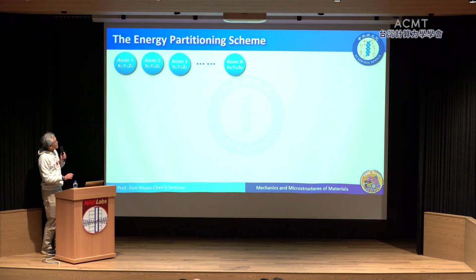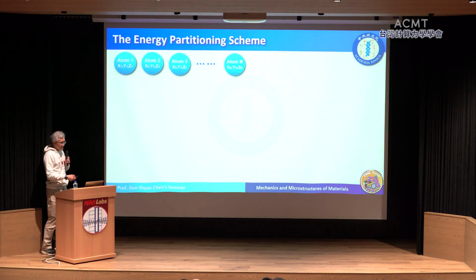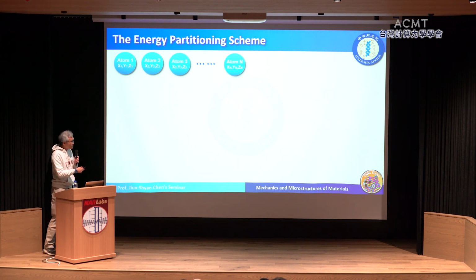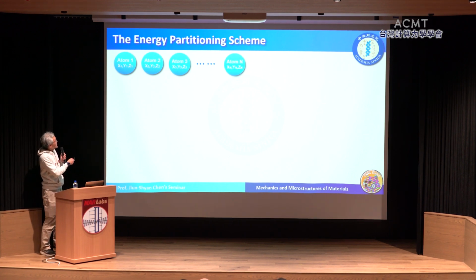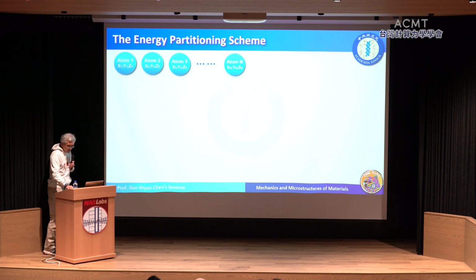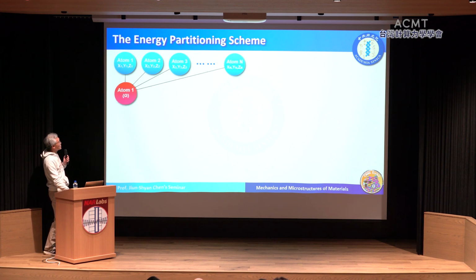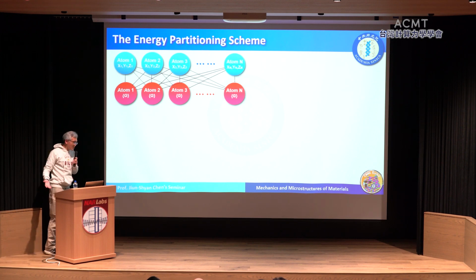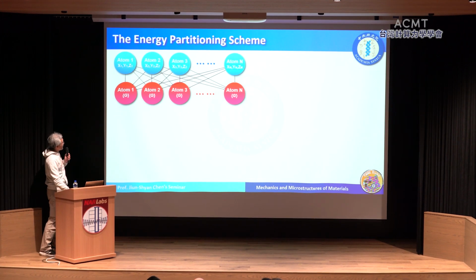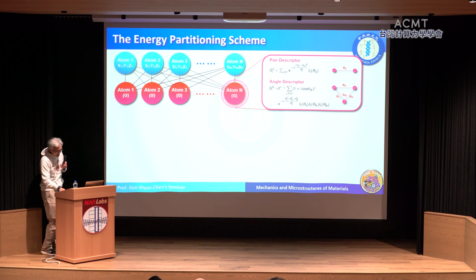Okay, so the first difficulty we face is, as you know, that in atomistic simulation, we need to have an interatomic energy model to describe the interaction between atoms in the system. This is the energy partitioning scheme proposed by Behler and Parrinello. Starting from the Cartesian coordinates of atoms, we can encode them into rotationally and translationally invariant vectors G, and they actually look like this.